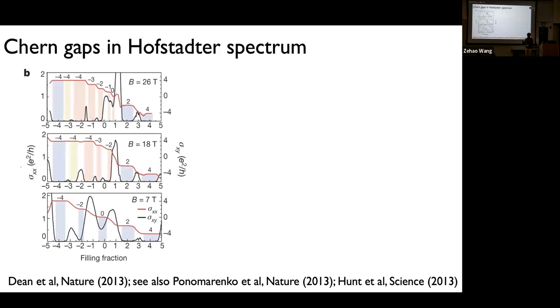They measure the sigma XX and the sigma XY. You can see that at low field, around 7 Tesla, you just see the plateau. It always goes the same way: 4, 2, 0, minus 2, minus 4. And when you start to approach 20 Tesla, weird things happen. Somehow the minus 4 plateau becomes wilder, and it becomes even wilder if you go to 30 Tesla. And this is already telling you that you have some anomaly happening.